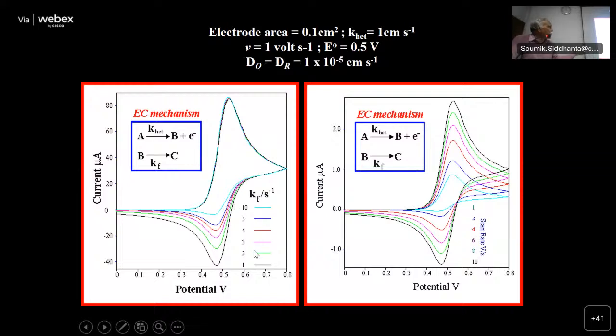Voltammogram with the variation of rate constant with the scan rate you can see. At some scan rate you get a beautiful reversible peak. Some scan rate you will see, no, it only looks irreversible. This side is so much suppressed. There is a small activity, it's not completely irreversible, but this variation is because of the variation of the scan rate as well as the rate constant. Essentially, Kf is the rate constant of the chemical reaction. K heterogeneous is the electron transfer rate constant. So a competition between these two, this could be irreversible, this could be reversible.